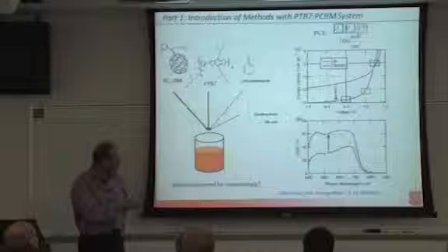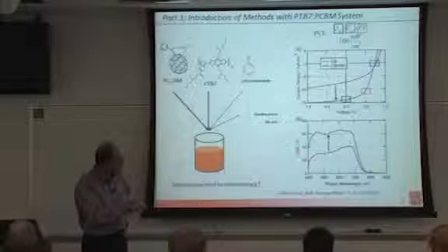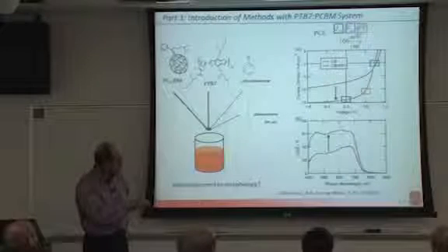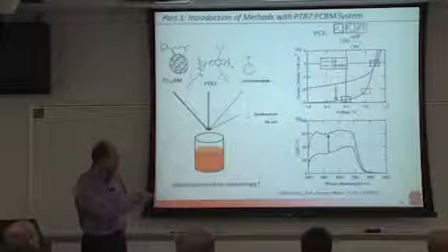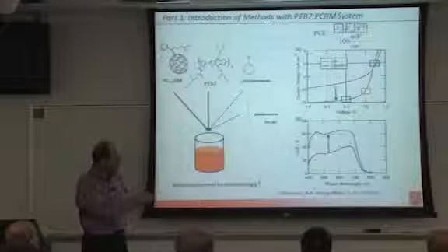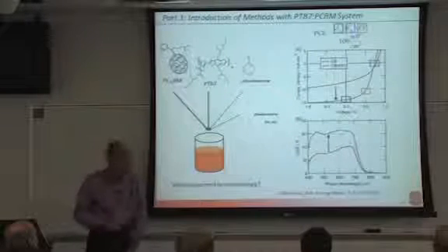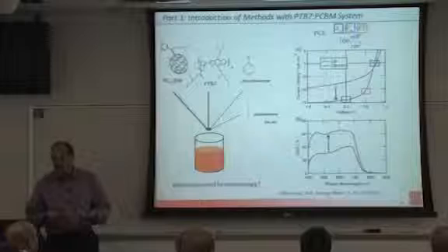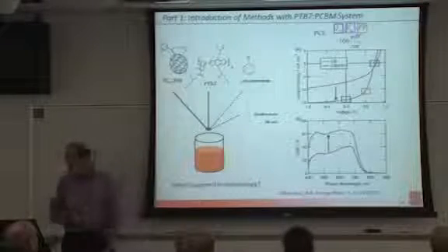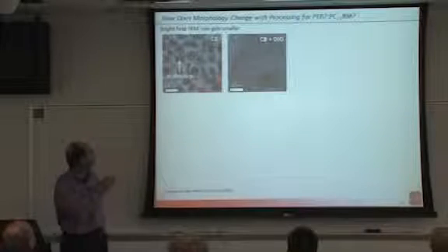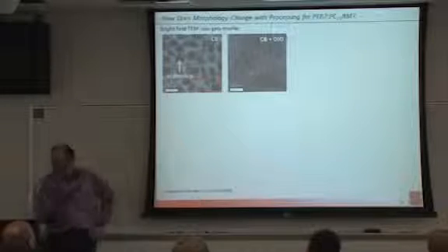We can also measure the external quantum efficiency. You see that goes up, and there's a little bit more improvement in the region of the PCBM near 450. Down here, that's the polymer absorption. So the morphology, something changes. What is it? Those are the questions that you would like to understand. You can use TEM. This is with and without. With and without. TEM gives you domains. It's hard to make out what you have here with the DIO.